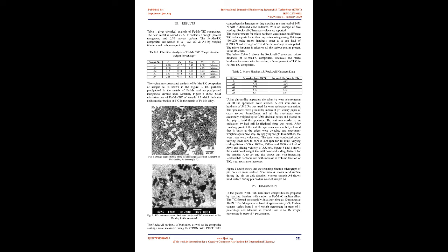The typical microstructural analysis of Fe-Mn-TiC composites of sample A3 is shown in figure 1. TiC particles precipitated in the matrix of Fe-Mn and no precipitated manganese carbide is seen. Similarly, figure 2 shows the SEM microstructure of Fe-Mn-TiC of sample A3, which indicates uniform distribution of TiC in the matrix of Fe-Mn alloy.